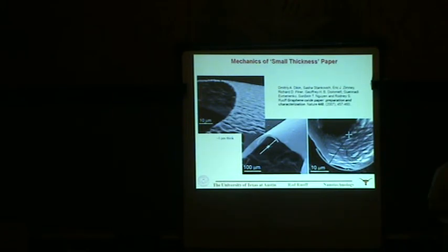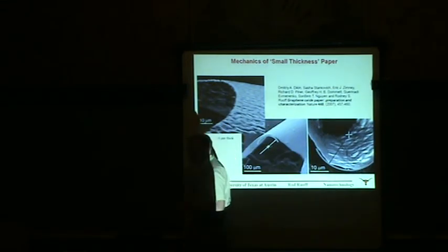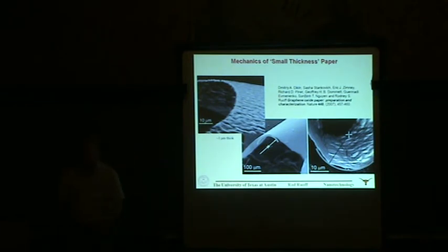And he started his talk by saying, I'm a physicist, I hate chemistry, but because I work on sensors and lead the sensor division, I have to know a little bit of chemistry. What they have done with these overlap and stacked platelets is make membranes where they get Q values as high as 10,000. So the quality factors that they get for mechanical resonance of these membranes made from overlap and stacked reduced graphene oxide platelets is much higher than the graphene itself. So when I come to my other talk, we'll see Q values only around 100 for resonating graphene.